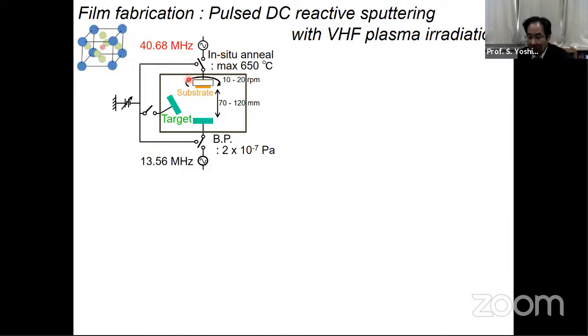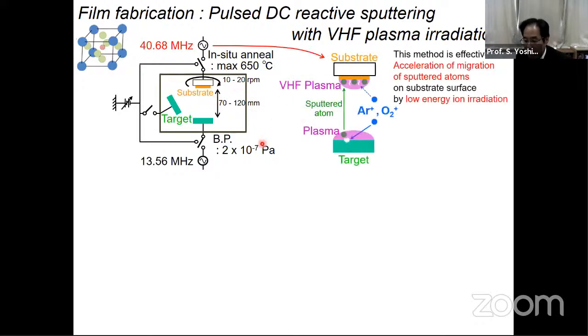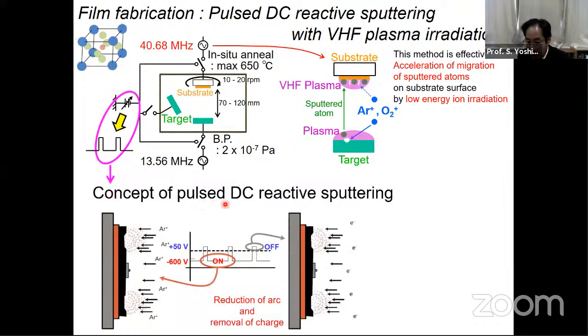If we use a normal film fabrication system, the film quality is not so good. So we have to change the fabrication system from the normal one. This is our sputtering system. This system has a high frequency electric source at the substrate. This electric source can generate high frequency plasma around the substrate. This plasma is very important for acceleration of the migration of the sputtering atoms on the substrate surface. And I newly introduced the pulsed DC sputtering system.